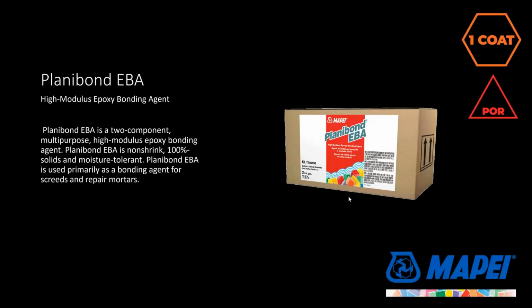Planibond EBA, high modulus epoxy bonding agent, is another one of these super products for grabbing onto concrete prior to the application of another self-leveling underlayment. We've also used these for crack management, crack isolation or crack bonding. We talk an awful lot about this process in some of our technical data sheets: chasing a crack with a saw using the appropriate PPE, opening it up, and using Planibond EBA to drip into these cracks and then cover it with a sand broadcast on top. So it's a great solution for that kind of repair going forward.